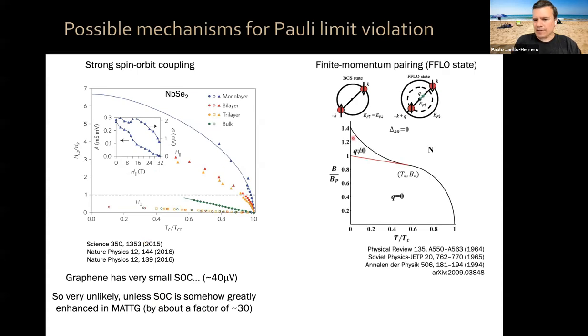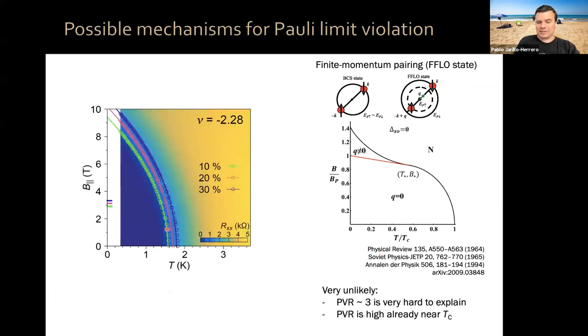Now, there is also something called FFLO states, finite momentum pairing, okay? That can also give you a violation of the Pauli limit, but it's a maximum violation of the order of 30, 40%, and only at low temperatures, below half of TC. However, in our case, we don't see a 40% violation, we see a 300% violation, and it's always present right away, at TC, okay? It's not that it starts to violate at low temperatures, it's always violating by a large factor, okay? So that's why we think that FFLO physics is probably not responsible for our data.